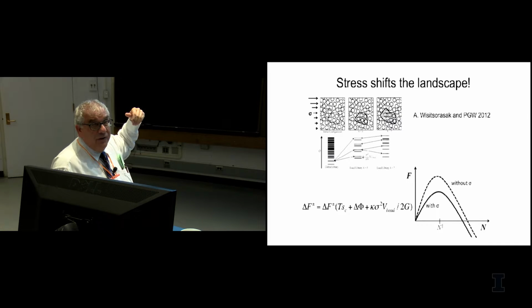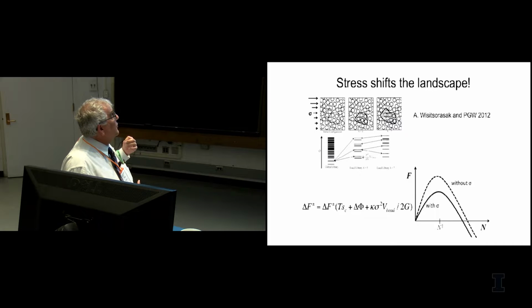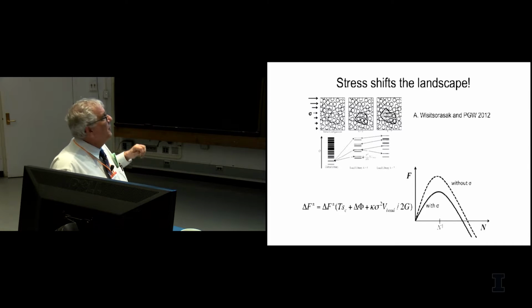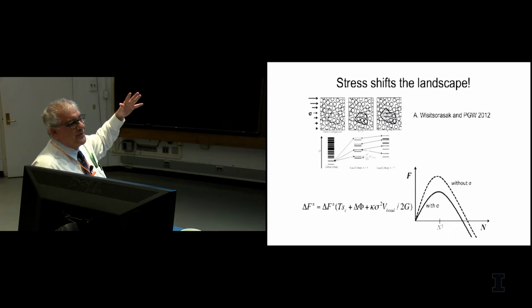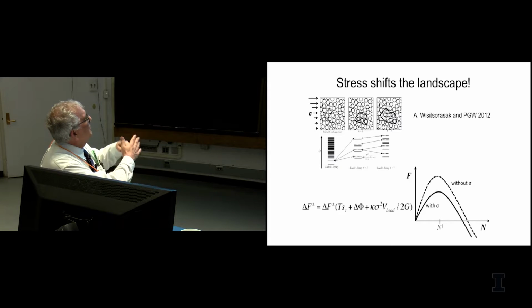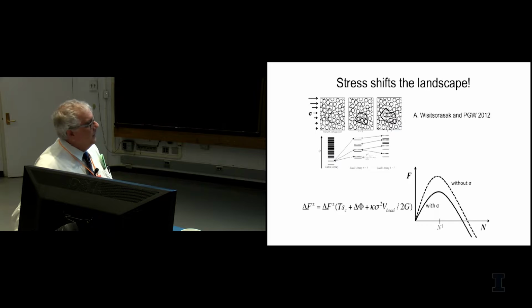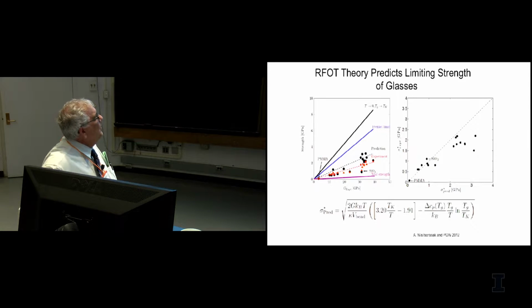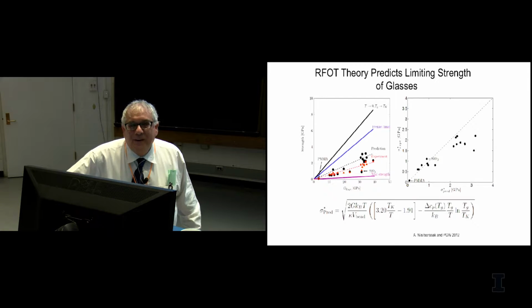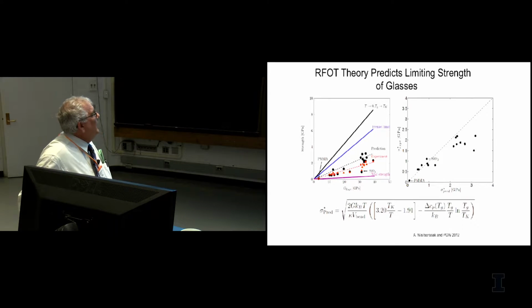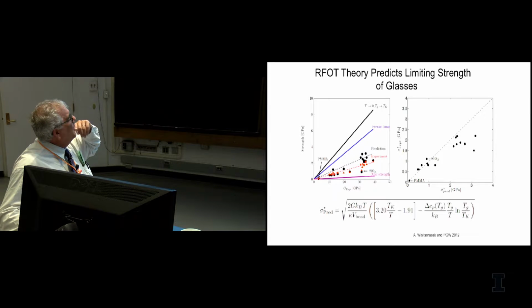And then on the other hand, you also can go to a non-stressed configuration. So you lose an amount of stress, an amount of energy proportional to the square of the stress. The coefficient in that is something that involves a calculation that would be familiar to anyone in damped. It's basically the calculation of the intrinsic viscosity, but for something with more elastic constants. It's elasticity rather than hydrodynamics. So this actually predicts the actual strength of glass. So this is the formula from Wisitsorasak's, in my paper. Wisitsorasak was one of my students at Rice.